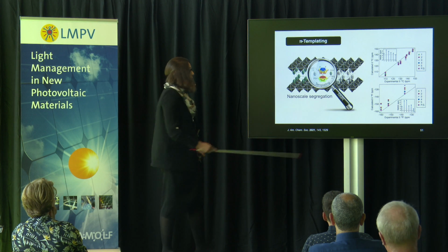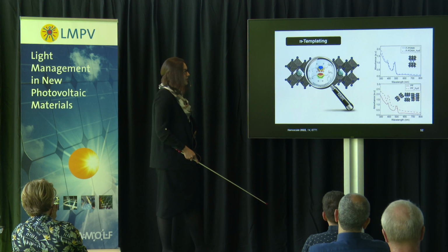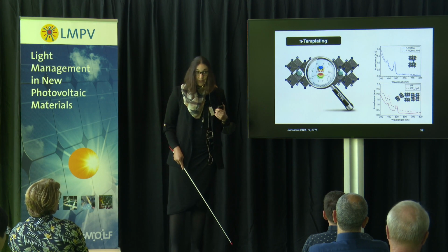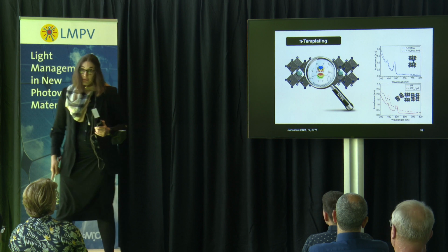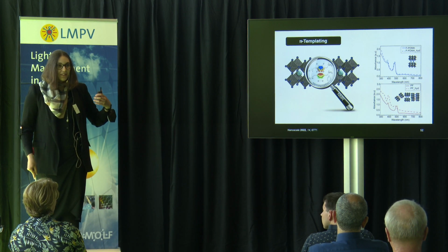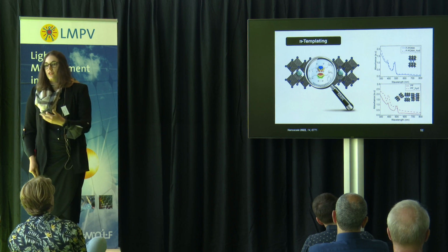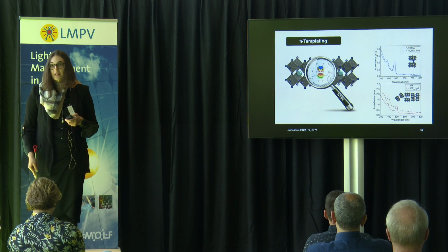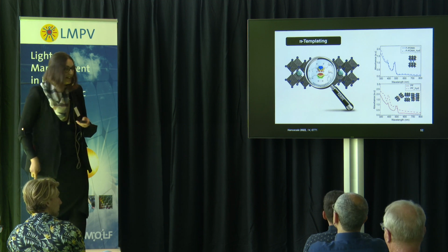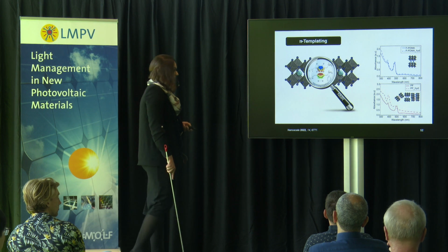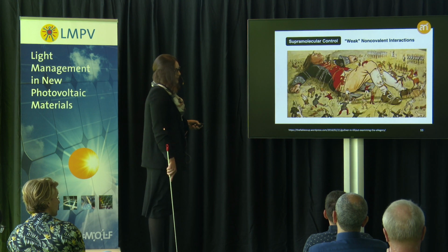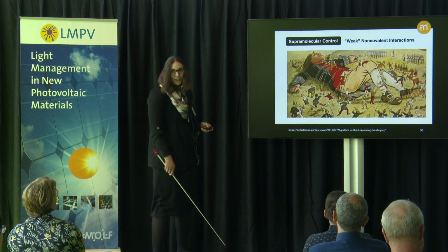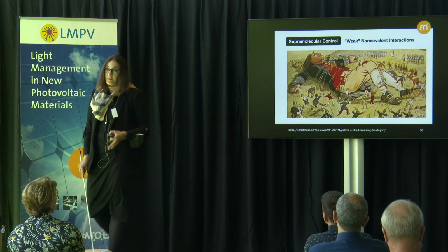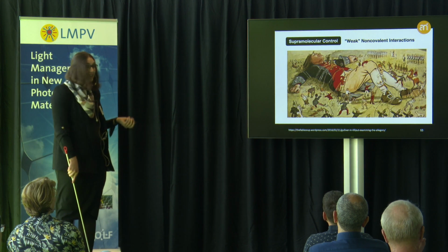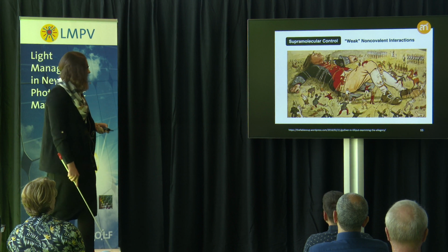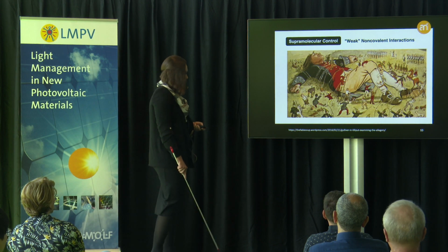And this is not only the case for these systems, but it's also general for more architectures, which really challenges our perspectives and brings a level of complexity when it comes to targeting their design, but implying the necessity to further look into these atomic level interactions to understand and identify the factors contributing to their effects in the materials and the resulting devices. This also highlights the main feature of these supramolecular strategies in general, which is that these weak non-covalent interactions, despite their weakness, are multiple in these materials, and as a result can and will make a difference. So it's worth looking more closely into understanding them to be able to control these materials.